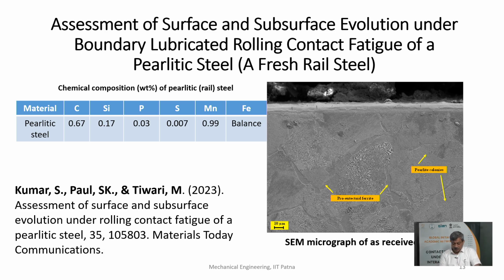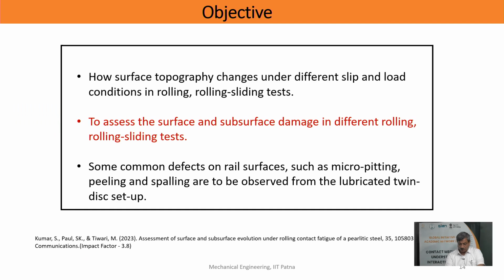calculated the ratio to find out lambda for boundary lubrication, measured the surface roughness, and done that. Now as we know, the material is pearlitic. So there is pro-eutectoid ferrite here, and you'll see that this is how the cracks start because of bending of pearlite and squeezing of this ferrite, and the cracks start from the grain boundary. So I think now rail systems all over the world, I don't know how it is outside, but they are trying to change over from this pearlitic steel, one of the reasons being the kind of failure which we are seeing in this, and it is happening on the tracks also.